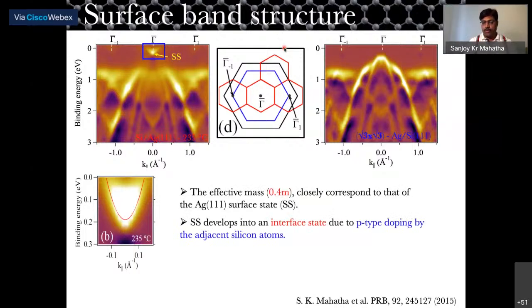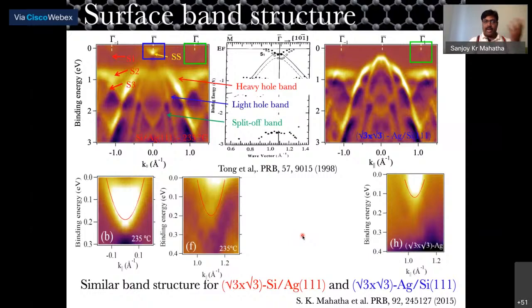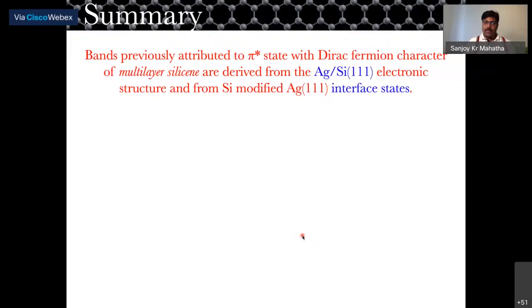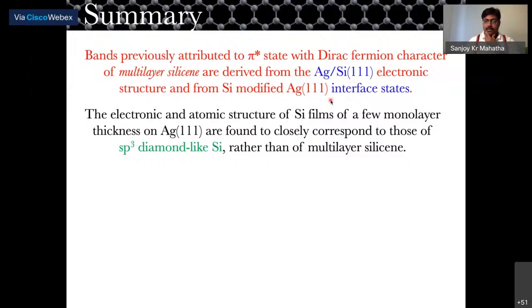And so at the end, what we wrote is that the surface state is basically developing into a kind of interface state due to p-doping of silver by the adjacent silicon atoms. So from here, what we can say is that the bands previously attributed to the pi star band, which were claimed to be coming from multilayer silicene, are derived from silver on silicon. Okay, and there is also a silicon-modified silver 111 interface state. And the electronic and atomic structure of silicon film of few monolayers or multilayer silicene looks like sp3 hybridized diamond film of silicon rather than multilayer silicene.